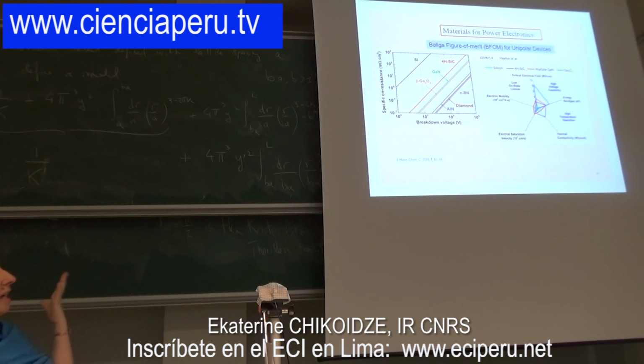And here is a landscape of materials, as a reference, where you have silicon and wide band gap materials like silicon carbide, gallium nitride, diamond, gallium oxide, and boron nitride. So what's of interest today in the lab is gallium oxide, and you see that theoretical curve. Gallium oxide's material performance is just behind aluminum nitride and diamond.